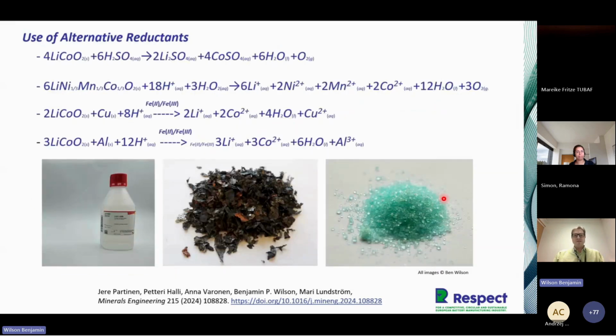So why these alternative reductants? Well, in fact, most of these NMC are quite easy to leach in the first instance, just with the regular acid, but some components of the NMC crystal structure are actually quite hard to break down. So the idea of using the peroxide as an extra oxidative agent, but actually the use of iron in conjunction with copper and aluminium can provide a reductive process as well, due to this electron shuttling between the iron and the copper and the aluminium. So you can get some electron transfer, which causes the oxidation and reduction process to be enhanced compared to without the presence of these metals.